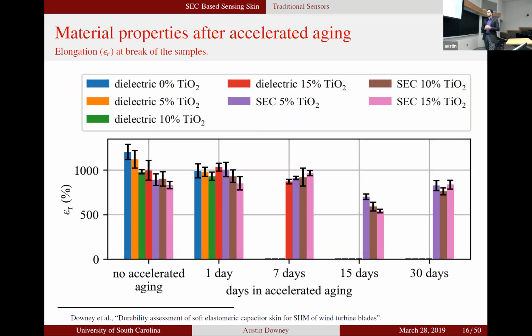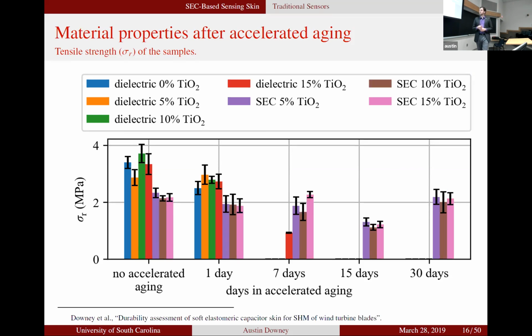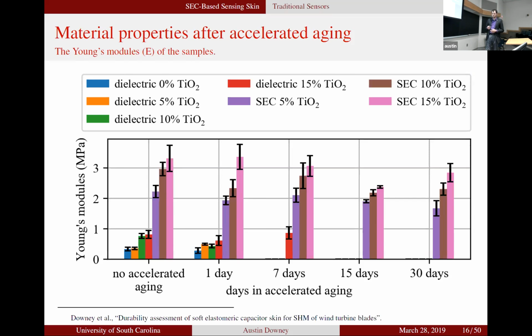Here's some mechanical testing values. We tested the dielectric without any TiO2 protection, and those do degrade, and that's why you lose these colors as we move over. But the pink, brown, and purple are the ones that are actual SECs, and those were able to hold their strain to rupture all the way to the end. Just another way to look at that is the stress that it took to rupture. Regardless of the aging, they're pretty constant.